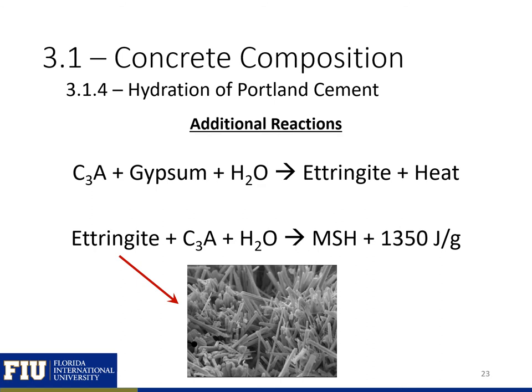Two additional reactions that occur are shown here. C3A reacts with gypsum and water to form ettringite and heat. Ettringite is crystalline, as shown, with needle-like crystal structure. If ettringite forms initially, there's room for it to grow, and also some of it will react with more C3A and water to form monosulfate.